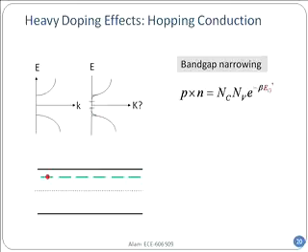Okay, so what is the distinction? The distinction is that there is a difference between band transport and hopping transport. And this is how. If you take a normal semiconductor which is lightly doped, 10 to the power 18, let's say, then the electron generally jumps up. The first point, let me come to that in a second, is that the gap has essentially narrowed because of the green states now. The band gap is no longer EG. It's a little bit less.